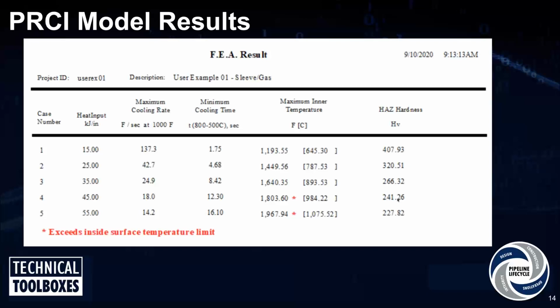And then the last column is the weld hardness, and that's how the model predicts or mitigates the risk of hydrogen cracking. Again, the model predicts your heat affected zone hardnesses, and then you have to compare that to your acceptable limit to determine whether at that welding heat input, that hardness is acceptable. So this is what a typical output screen looks like. Can we go to the next slide, please.